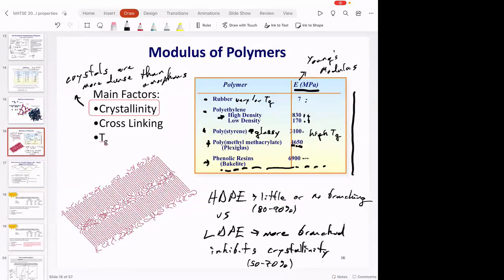So polystyrene has a Young's modulus of 3,100 megapascal, and polymethyl methacrylate has a Young's modulus of 4,650 megapascal. Which polymer relaxes faster, polystyrene or PMMA? Polystyrene. It's softer, or it has a lower modulus, so it's more flexible, and so it will relax faster. So it will creep more, and it'll have more stress relaxation. Does that make sense? Yes.